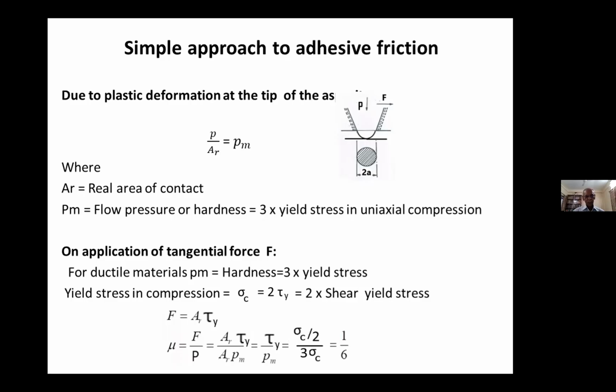This will be true only for very ductile material where hardness is 3 times the yield stress, and yield stress in compression is twice the shear yield stress. For ductile material, this is quite true, and P_m, or the hardness, being 3 times the yield stress in uniaxial compression is also true. So for this kind of material, we can safely say it is 1/6, but this is not sacrosanct. It does not apply everywhere. It's just to explain what adhesive friction is. So we'll stop here today. We'll take it up more in the next class.